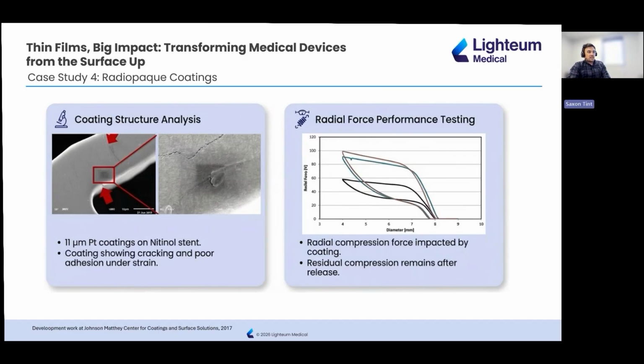Even more concerning, if you look on the chart on the right, mechanical testing showed that the presence of the thin platinum layer actually changed the radial force behavior of the stent. After compression, it didn't fully recover, and it required more force to close. So the coating solved the visibility problem, but broke the mechanical performance of the device.